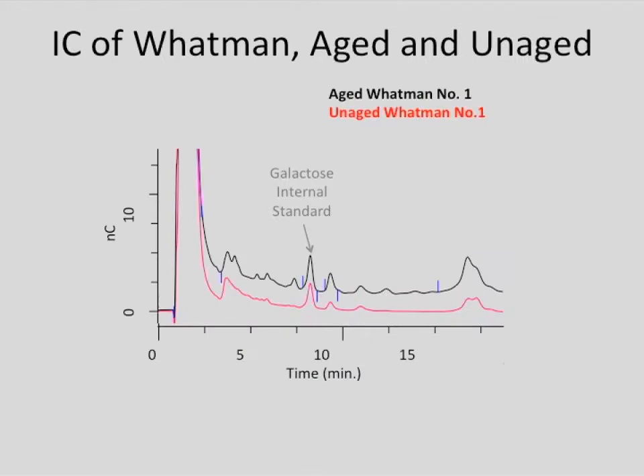Here's an example, not the prettiest, of one of our ion chromatography measurements, showing what just Whatman paper that's been aged in air looks like versus unaged Whatman paper. We always put a galactose internal standard in, so we have something to compare to. The red line is the unaged paper—it has some free materials in it that are ion chromatography active, shown here and here. Those got a little bit bigger in the aging process, so we are degrading the Whatman a little bit just by having it in air.